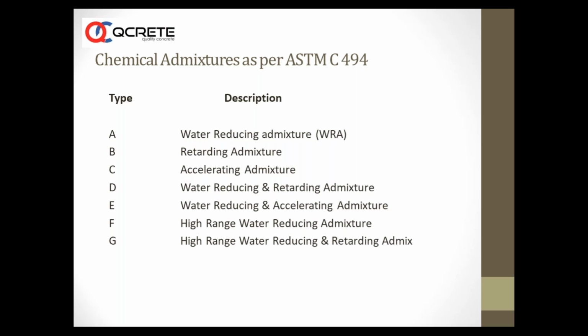A description of different types of admixtures is given in ASTM-C 494. Type A is water reducing admixture, which is a simple plasticizer, giving a water reduction of about 5 to 12% with a dosage of about 0.3 to 0.8%.